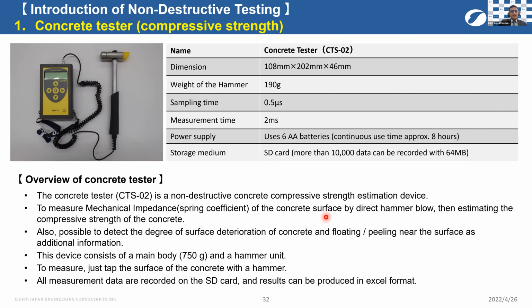Similarly, the concrete tester is also a non-destructive concrete compressive strength estimating device. It can be used to measure mechanical impedance or spring coefficient of the concrete surface by the direct hammer blow, then estimating the compressive strength of the concrete. In addition to compressive strength of concrete, it is also possible to detect the degree of surface deterioration of concrete as an additional information. This device consists of a main body and a hammer unit.